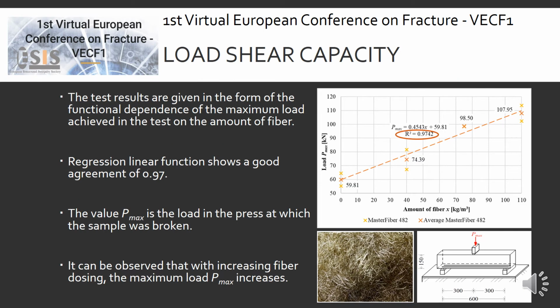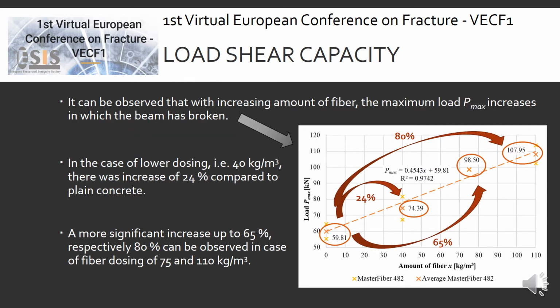The test results are given in the form of the functional dependence of the maximal load achieved in the test on the amount of fiber. Regression linear functions show a good agreement of 0.97. The maximum load is the load in the press at which the sample was broken. It can be observed that with increasing amount of fiber, the maximum load at which the beam broke increases.